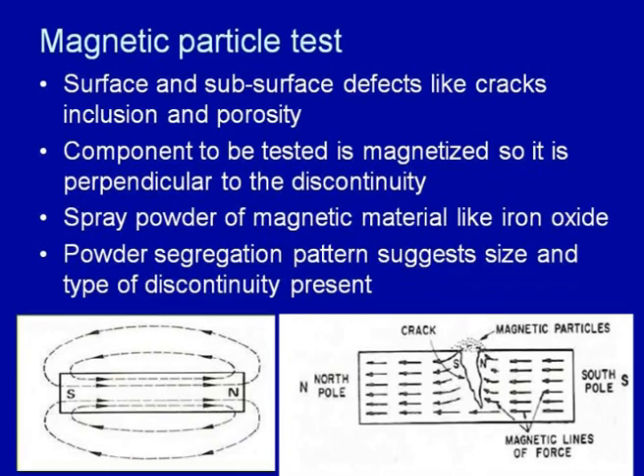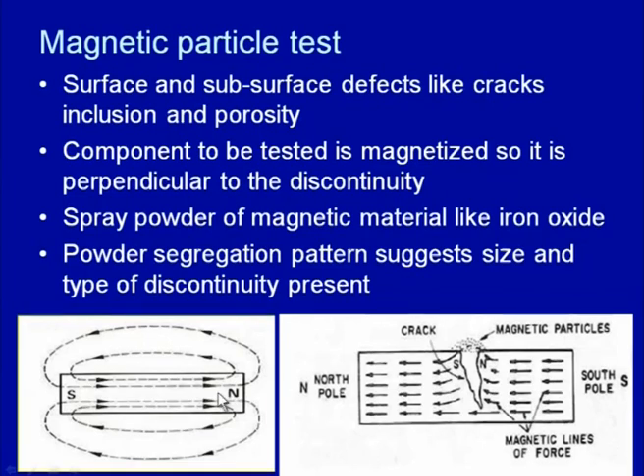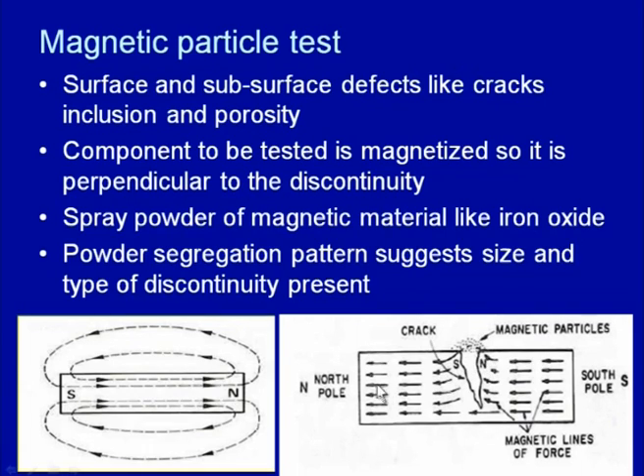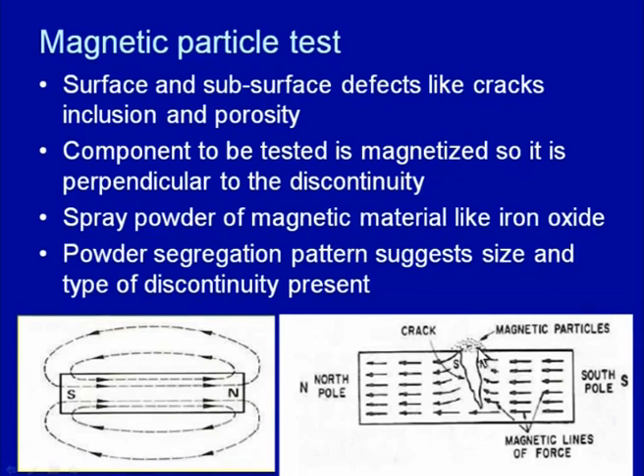So, here you see the normal magnet without any defect, where magnetic lines of force are passing from N to S, and the cycle is completing. But when there is a defect in the component, the magnetic lines of force start leaking from the location of the defect, and it forms two additional poles. When we sprinkle the powder particles, they tend to cluster in the areas where the magnetic lines of force leak. So, by seeing the pattern of segregation of the powder particles and the size of the segregation,